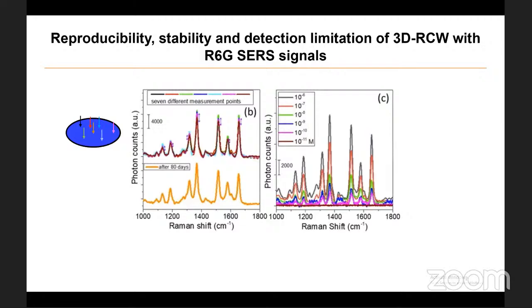SERS measurements were performed on 7 different positions and averaged. The spectra from the 7 positions were consistent as shown. The stable nature of the platform is also evident from the figure, where the SERS measurement was performed after 80 days. Furthermore, we can detect R6G with molar concentration close to the picomolar level.